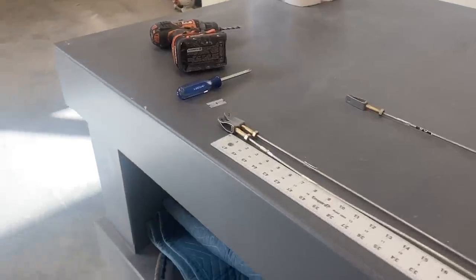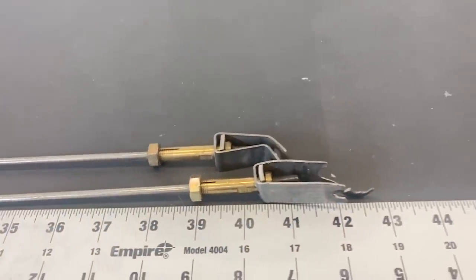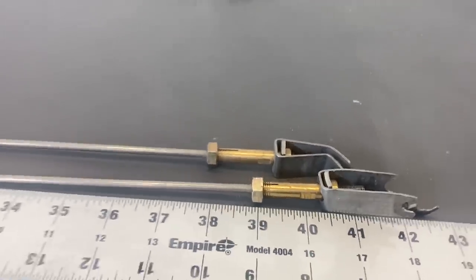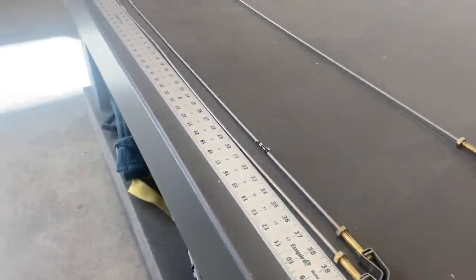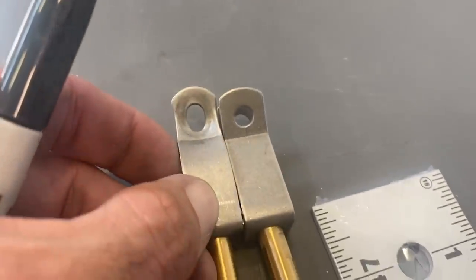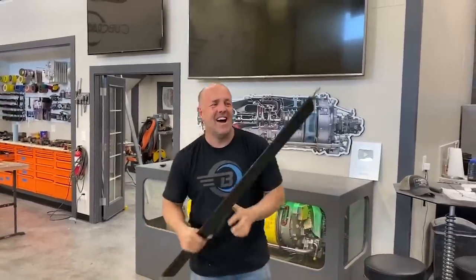What's really amazing is when I set these two wires together, a factory one that hasn't been pulled and the one that broke, it is now over an inch longer. And the carbon fiber tube, when I measured it, returned to its original length, and even at max pull, nearly 4,000 pounds, had almost no deflection at all. Okay, guys, I'm way excited.